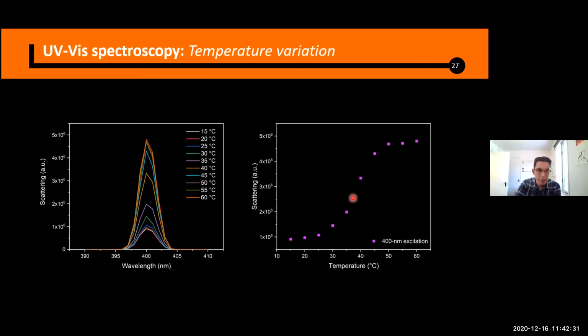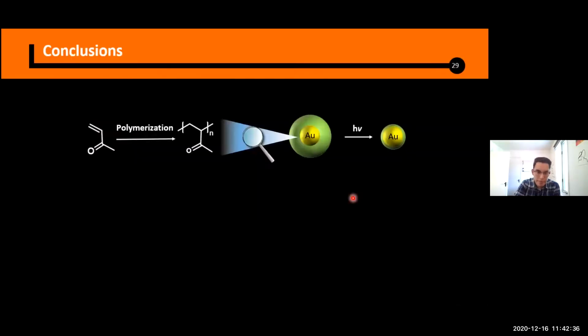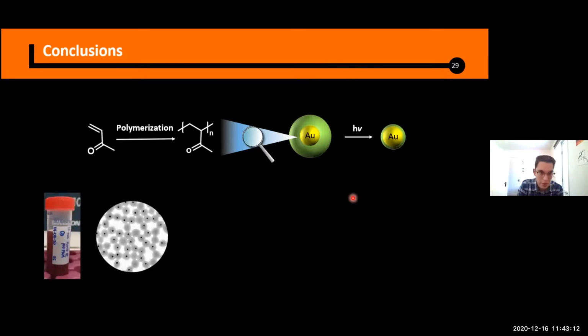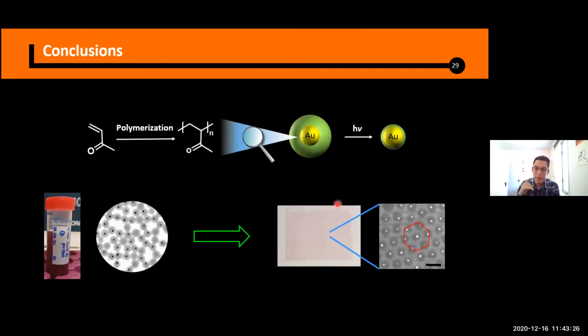So just to sum up, I would like to say that a new plasmonic-based light-sensitive hybrid material has been developed, and these spherical gold nanoparticles coated with NIPAM have shown very promising behaviors in terms of their thermoresponsive capability, and also the reversibility that they have. So what I'm working on now is how we can transfer these hybrid particles that are in solution, as I show you here in the pictures, to a substrate, in order to start developing either the light-activated membrane and also the light-driven pumping systems.